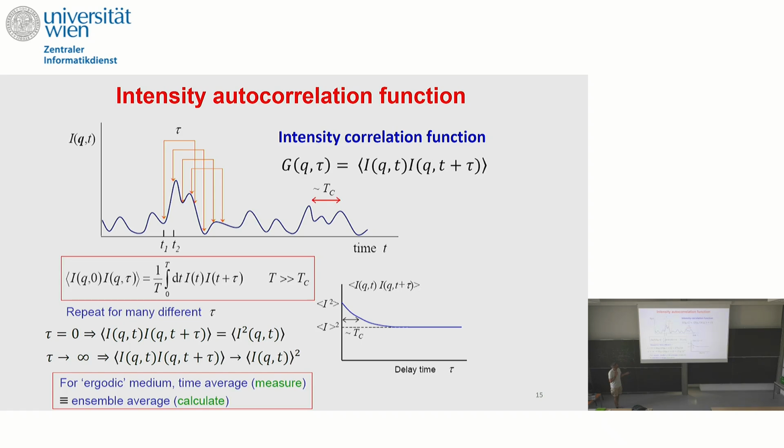Okay, just to give you a feeling of the timescales that are involved, I told you the duration of the time average of your experiment has to be much longer than the characteristic time that you measure here. What is much longer? Well, if you are super sloppy, it's like 100 times longer, but this is really bad. You will get super noisy data. If you are so-so, you will do 1,000 times. If you want really good data, you will do 10,000 times, okay?